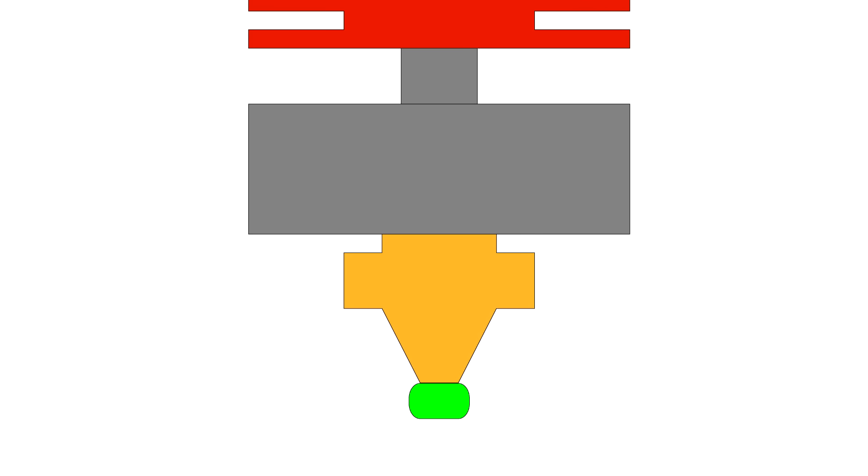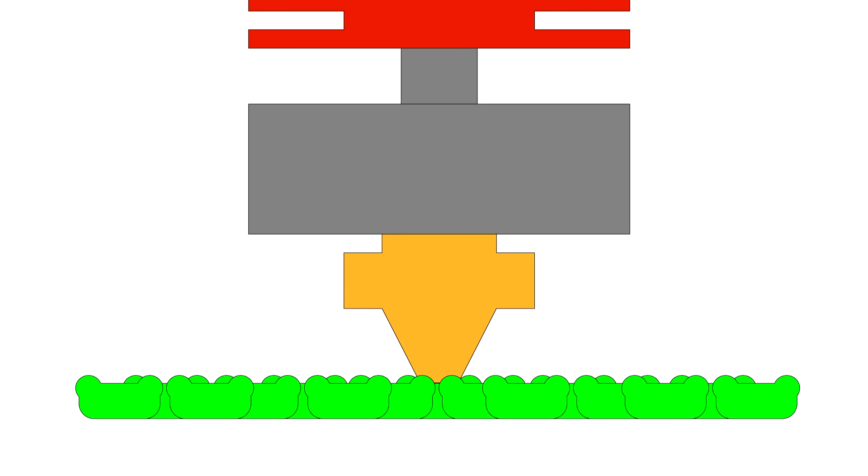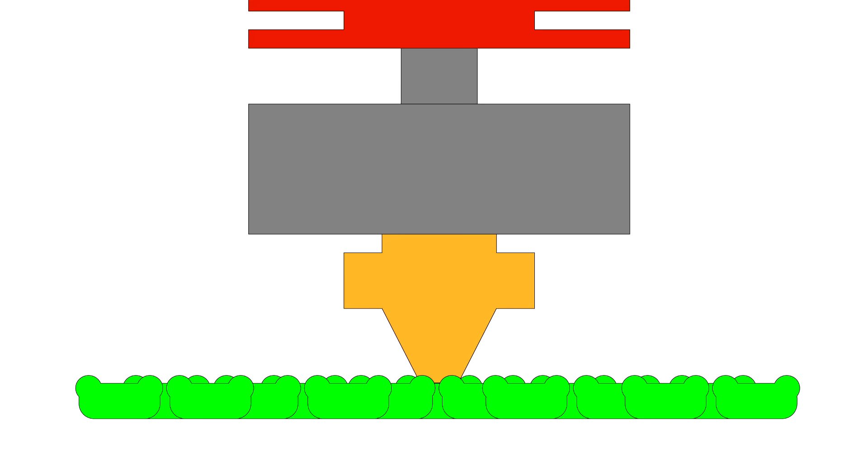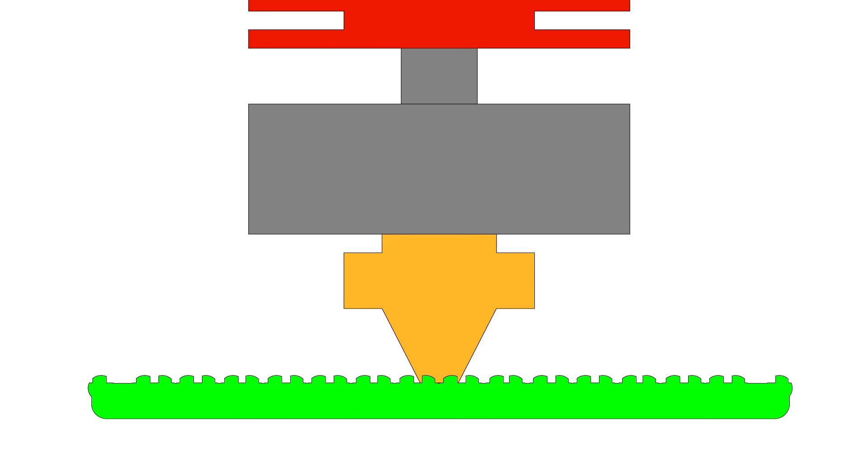The first part of Matt's technique is to massively over extrude, so instead of a neat blob, the plastic oozes up and around the nozzle higher than it should. As the top surface continues, there's going to be more and more of these lumpy bits extending above where the surface would normally be, but thanks to the different infill pattern that limits the length of the extrusions. As new extrusions are laid down, the tip of the nozzle is going to scrape through the plastic and leave a pattern behind. Except for the very last extrusions, where the full width of the nozzle will leave a slightly wider gap.